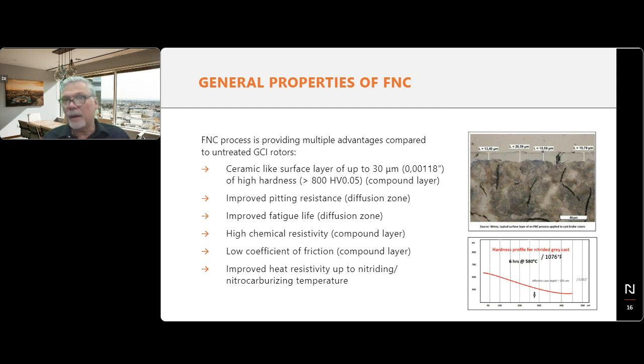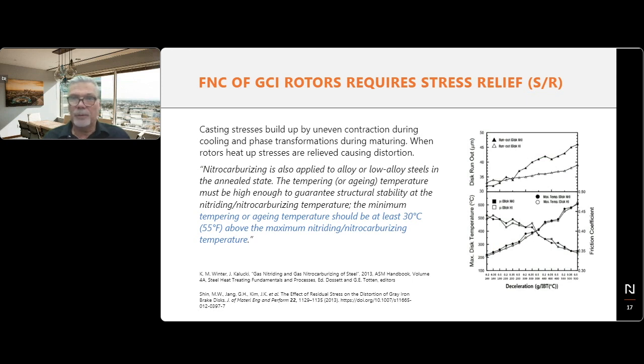And this is why cast iron is called gray cast iron, because part of the carbon content, which is relatively high in this type of cast iron, well, part of this carbon will appear as flakes, and those flakes will play an active role in the way the material behaves. Well, also it is very important to say that cast irons do mature. It's a very special group of materials. During cooling, after casting, there are many transformations going on, phase transformations. Of course, there is a physical cooling down and stress formation.